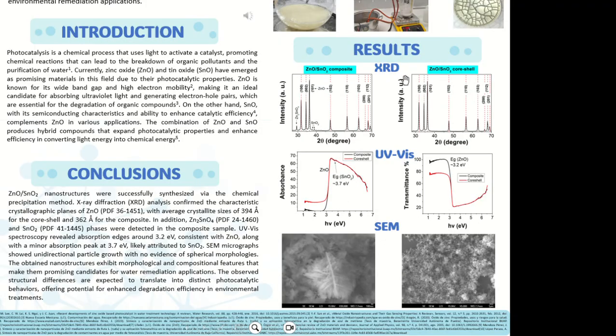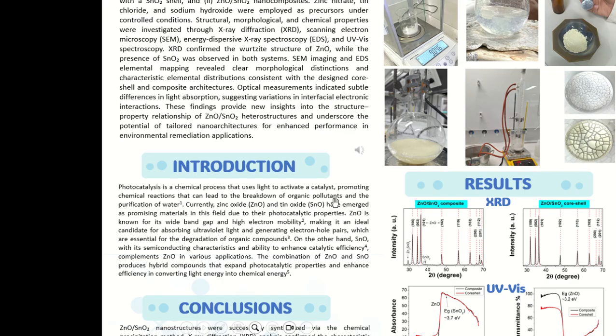XRD confirmed the Wurtzite structure of zinc oxide, while the presence of tin oxide was observed in both systems. SEM imaging and EDS elemental mapping revealed clear morphological distinctions and characteristic elemental distributions consistent with the designed core shell and composite architectures. Optical measurements indicated subtle differences in light absorption, suggesting variations in interfacial electronic interactions. These findings provide new insights into the structure-property relationship of zinc oxide-tin oxide heterostructures and underscore the potential of tailored nanoarchitectures for enhanced performance in environmental remediation applications.